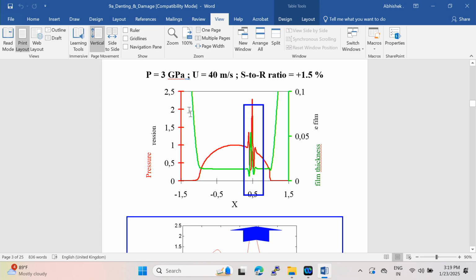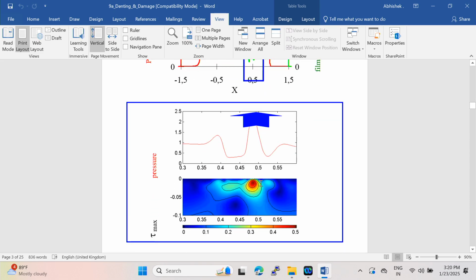Then in green you have the deformed geometry within the contact. You can see here the dent. Then there is a dent with two shoulders. And in red you have the pressure within the contact when the dent is coming into the contact. Here there is a small slide-to-roll ratio, which is 1.5%. This is the ratio between the sliding speed and the rolling speed. And after that, you can calculate the stress distribution within the material.